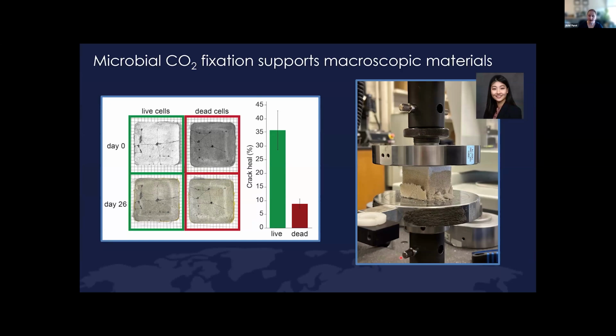Similarly, if we think about how we can use these microbes for improving construction, this was actually a surprise to me, but around 9% of global CO2 emissions are specifically from the construction industry. A lot of that is from transportation of materials and hands-on need to fix things. So all we did was dry mix in some of our microbes coated in these protective materials. When we do that at 0.1 weight percent, in a month, we see about 35% crack healing. You can see that in these images. The live cells, you can see the white filling in here, versus the dead cells, where we see very little to no healing.